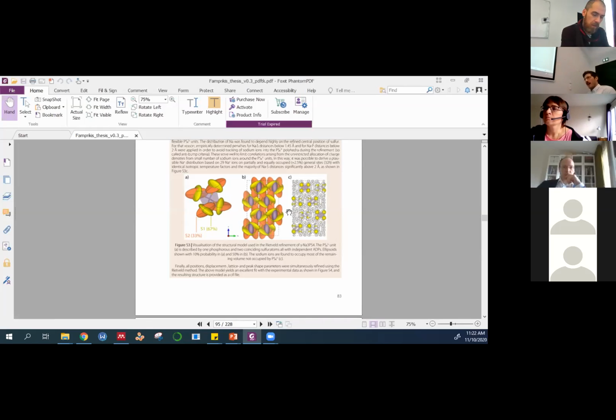You mentioned that the anisotropic displacement parameters should be able to capture the motion. I do not agree with this necessarily. The Debye-Waller factors were designed to describe harmonic phonon-like behavior, right? But in connection with what I answered to Marnix before, if you look at the molecular dynamics and the inelastic neutron spectra, you cannot really say that these PS4 materials engage in what we would call classical phononic behavior in a solid. So in that sense, I think it's more of a limitation of the Debye-Waller formalism rather than an error in using it here. I would be surprised if it did make sense, to be honest.